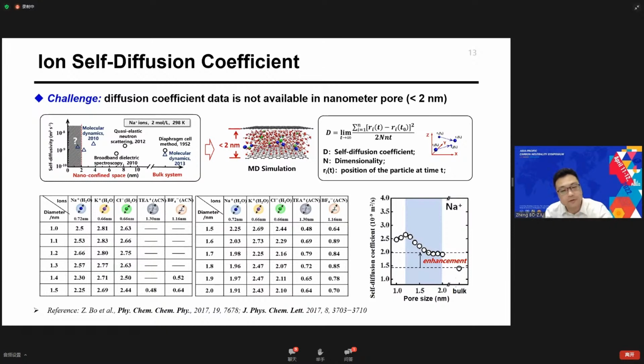Ion diffusion plays a key role in determining electrolyte conductivity and power performance of supercapacitors. However, most ion diffusion data is limited to bulk solution and pore sizes larger than 2 nanometers. So we use MD simulation to get the diffusion coefficients of ions confined in neutral and charged nanopores, that is less than 2 nanometers.